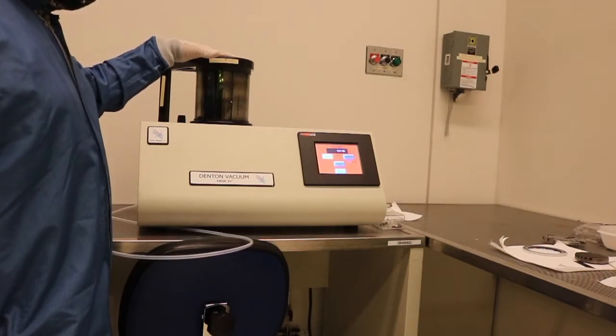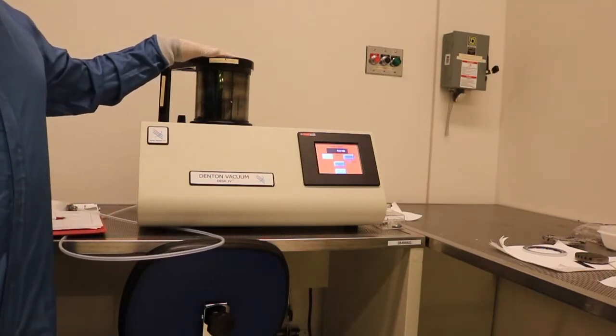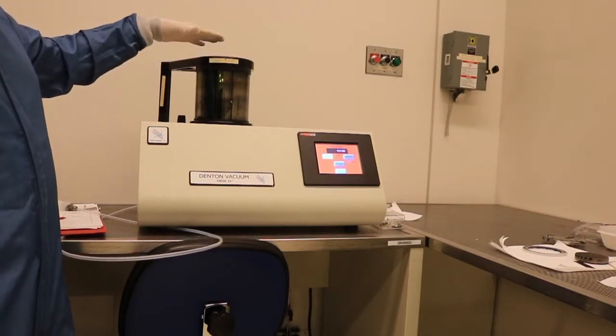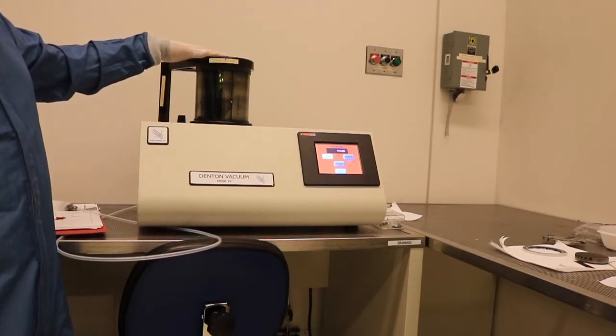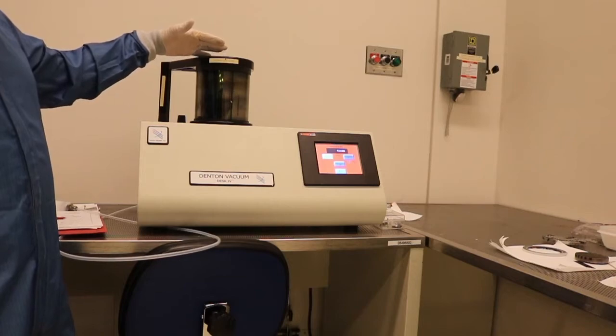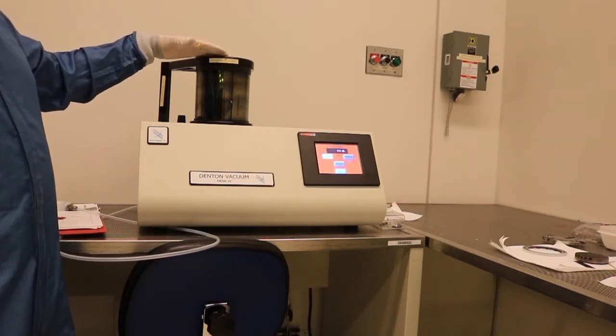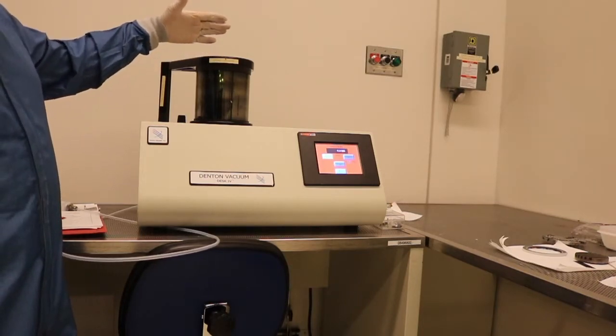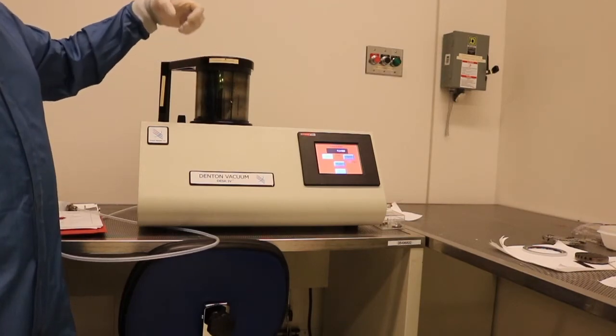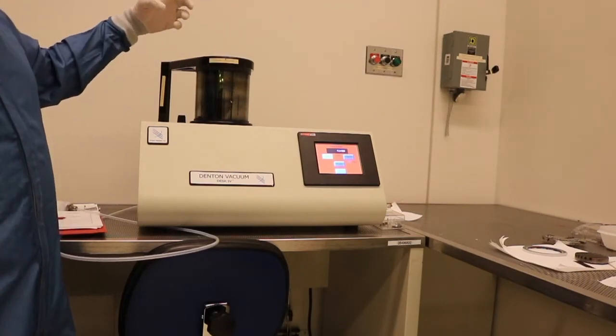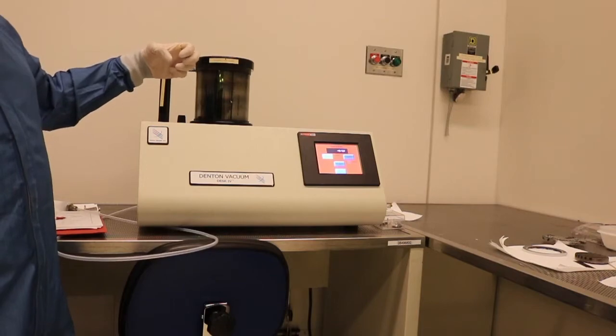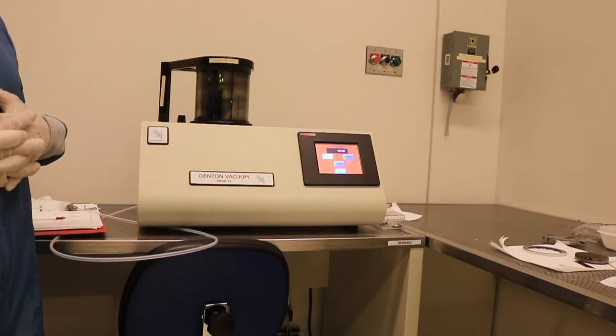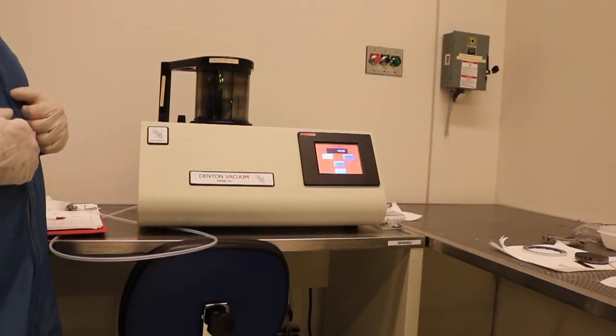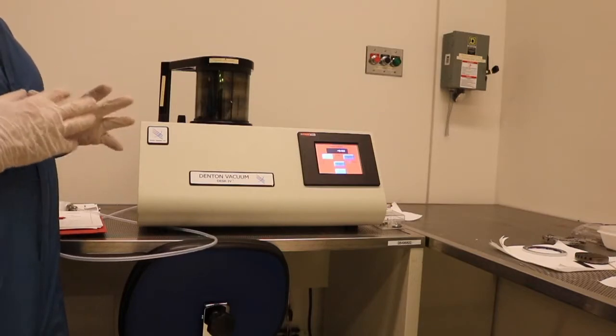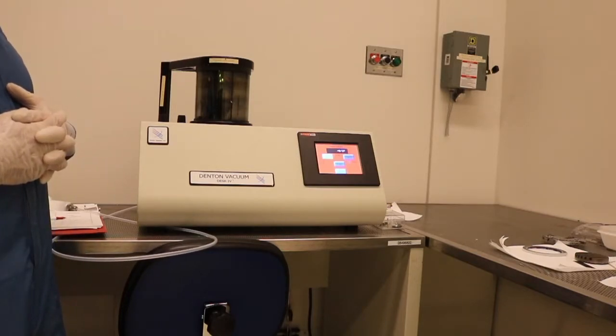And there are a few things to keep in mind when you do this. Typically, we've found that the best possible coatings come with a relatively slow coating. Generally, if you coat with a very high power and a very high gas flow, the material that deposits on the sample typically becomes very clumpy. And a lot of times it will look like dried mud that has started to crack. You don't want to see that type of surface because that will typically obscure the features that you're looking for.